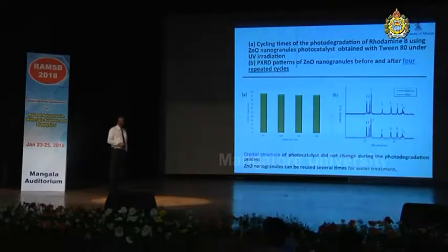Well, we have recycled these photocatalysts for repeated usage. We have tested about 4 times, but still the product did not change its phase. This is before and after the X-ray diffraction, I mean, after 4 cycles of the usage. So the materials did not degrade. So that's the advantage of these materials.